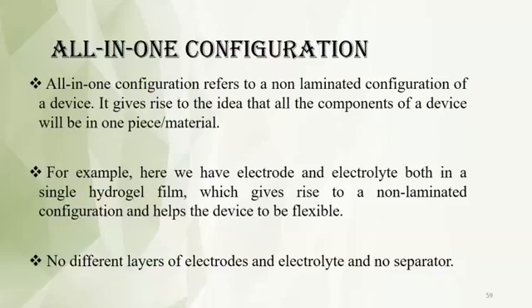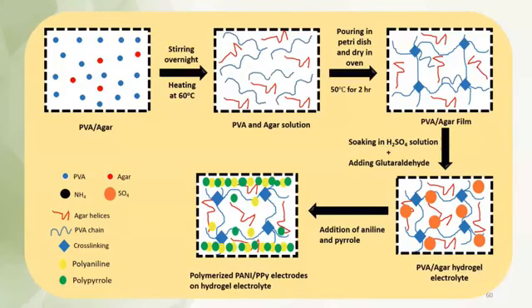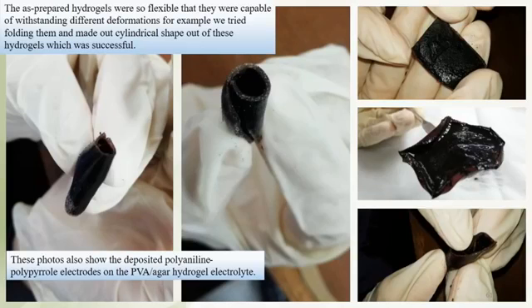And recently, we have also introduced a new type of hydrogel, which we call as all-in-one configurations. So we can see here, the hydrogel is prepared as an electrolyte system, and then we coat the electrode on top of that by using the PANI and polypyrrole. So in other words, the electrode will sit on top of the electrolyte. So the whole system, which is the electrolyte and electrode, is all made in an all-in-one configuration, which we call as the hydrogel configuration.